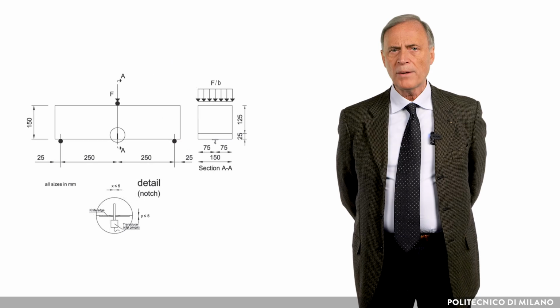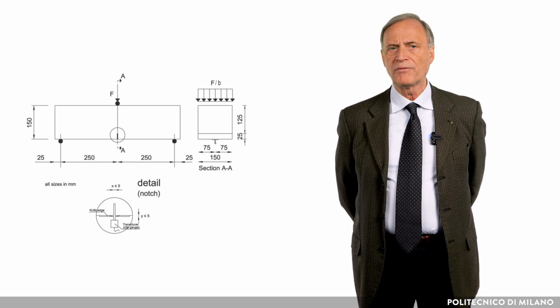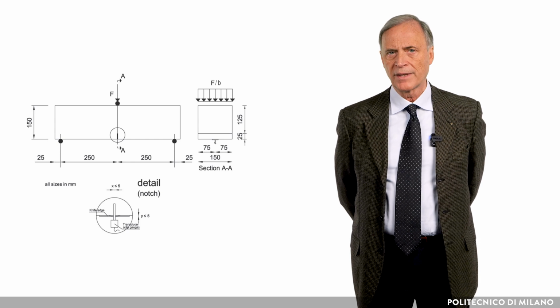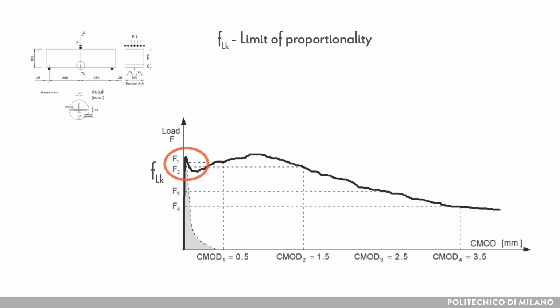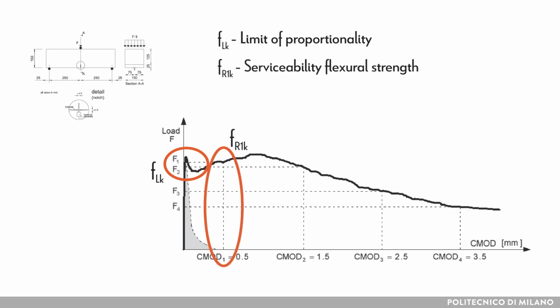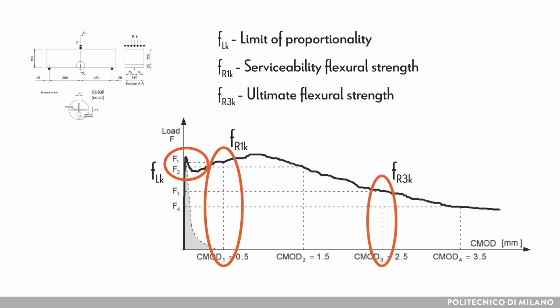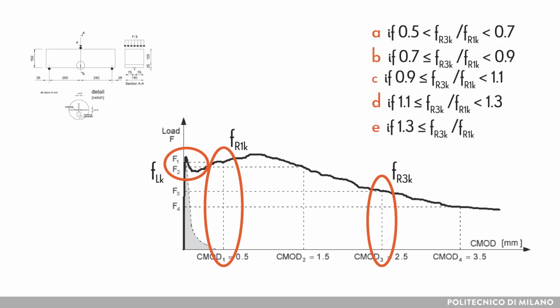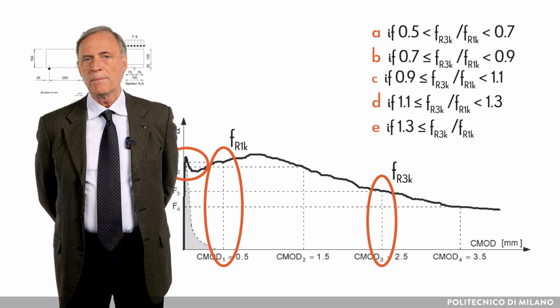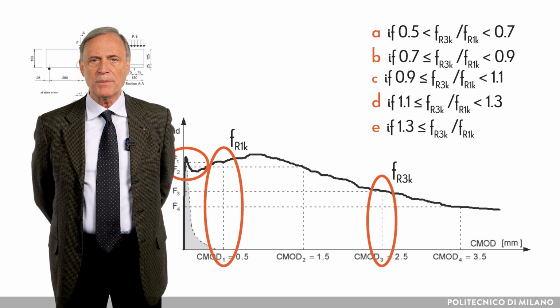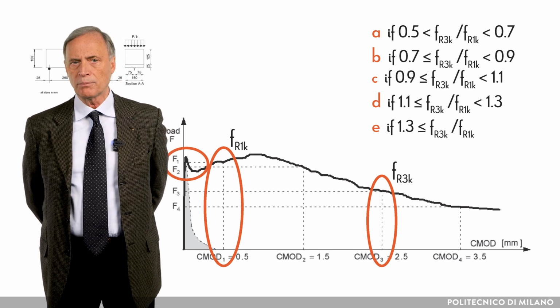Fiber-reinforced concrete performance in bending is measured by means of a 550 × 150 square mm notched prismatic specimen to reproduce a three-point bending test. Three parameters qualify the mechanical response of the material: the limit of proportionality f_Lk, the serviceability flexural strength f_R1k associated to a crack opening of 0.5 mm, and the ultimate flexural strength f_R3k associated to a crack opening of 2.5 mm. In particular, the f_R1k value and a letter in the range A to E, used to recognize the ultimate residual strength versus serviceability strength ratio, classifies the mechanical behavior of the material. Starting from the classification, it is possible to identify, by means of equilibrium equations, the pull-out resistance offered by fibers in a uniaxial tension and the constitutive law in uniaxial compression.